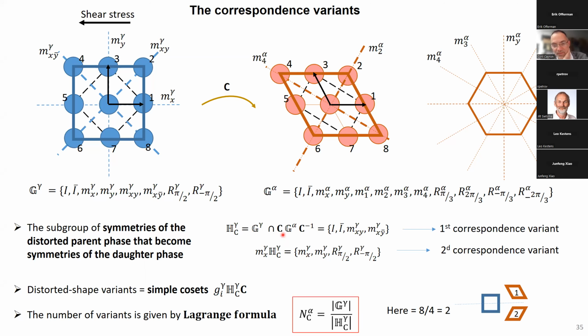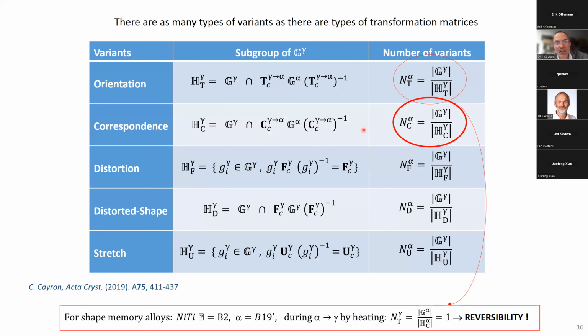Okay, so in that case, what is important is that we can calculate the correspondence matrix as we did for the orientation matrix, and we can here realize that we have two correspondence variants. So we have as many variants as we have types of relationship between the parent phase and the daughter phase. We have variants for orientation, variants for correspondence, variants for distortion.